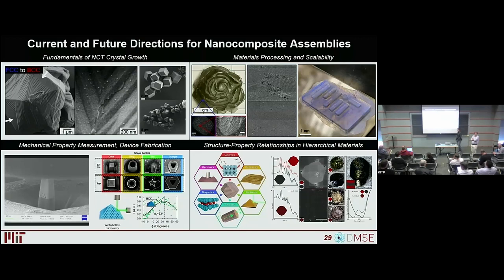Yeah. So those are all great questions. So the simplest one, the temperature is variable. It depends on the particle size and the polymer length, but to give you a sense, it's anywhere from 4 degrees C up to 100 degrees C. Below that, obviously, it's difficult to work with. Above that, you start to boil off the solvent. But we tailor that by changing, say, larger particles are higher temperature, longer polymers are lower temperature, and so on and so forth. But it's generally fairly low temperature conditions restricted by the solvent.